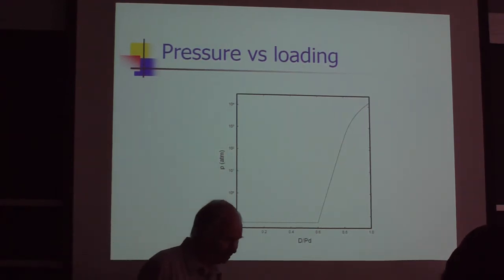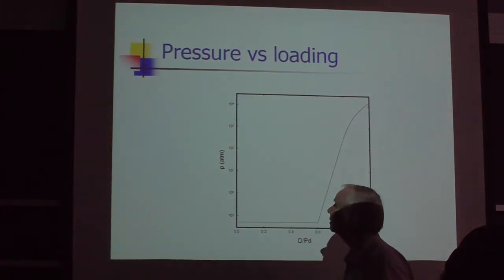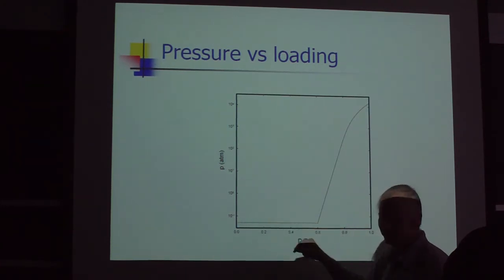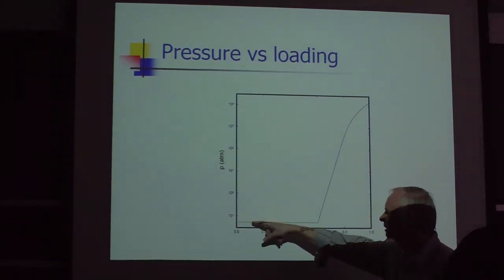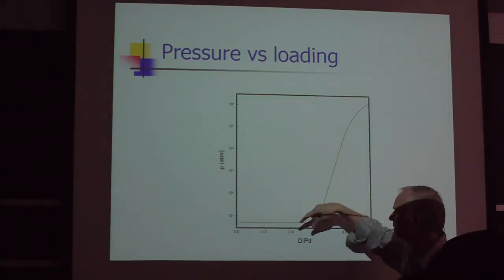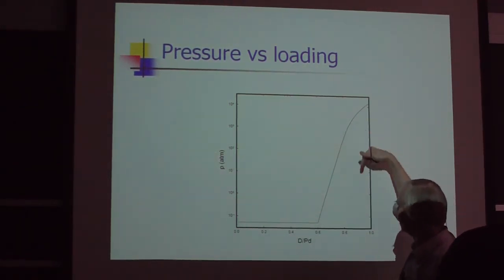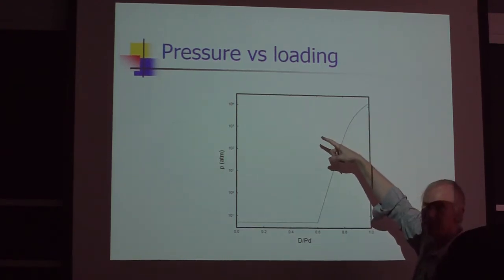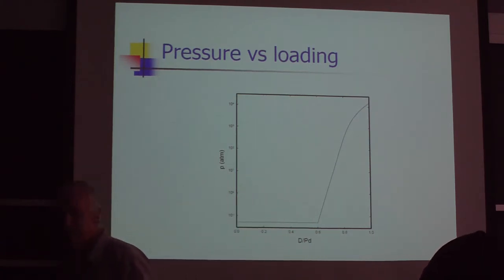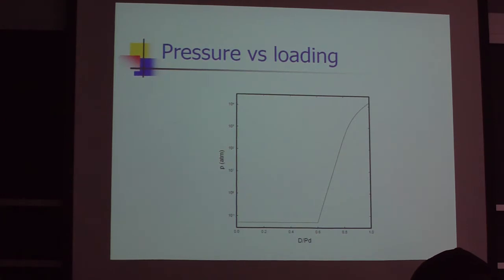So I've constructed—I took a lot of data and I was working on a thermodynamics model to put it all together. So I've got one atmosphere here, and I go up to here, so loading of one, I'm up over 10,000 atmospheres. So if you want to load palladium to one at room temperature, you've got to be prepared to bring 10,000 atmospheres to bear. And that's not a non-trivial thing.